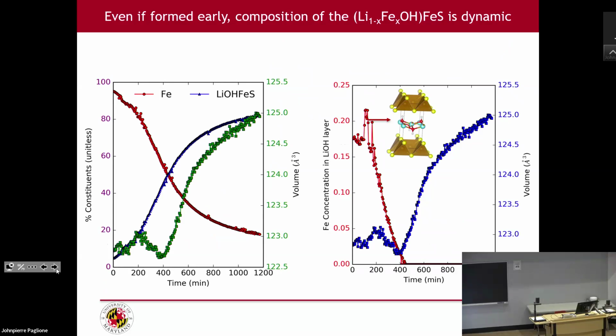And this is just one of the results. This is how the iron goes away, and then the product comes in. And then we're able to see that the iron substitution in the lithium hydroxide layer actually starts out near 20% and then drops out, okay? And so this is one of the reasons maybe sometimes you get irreproducibility in results. Sometimes you get a superconductor, sometimes you don't.